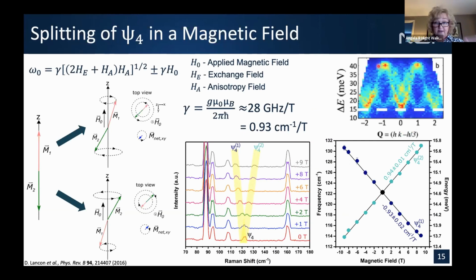Furthermore, we look at our neutron scattering data, not ours, data from the neutron scattering groups. And again, what's neat about complementary Raman and neutron scattering is the neutron scattering guys can see the entire Brillouin zone. We, of course, are quite limited around angular momentum equals 0, but that's also where their signal isn't as strong. So it's very complementary. But you'll see here, they saw what appears to be a magnon at about 15 meV. And if we just convert that simply, it's on the order of 120 wave numbers, which is where we see our feature. So we're quite confident that that is a magnon.